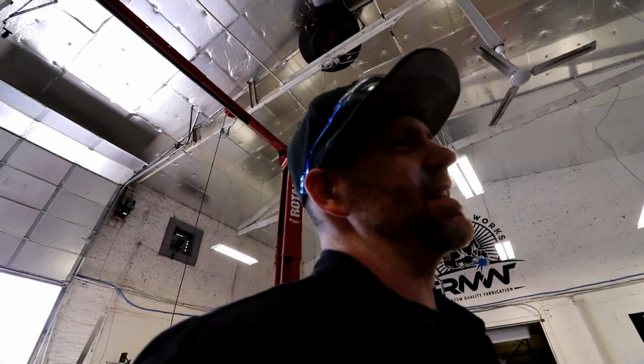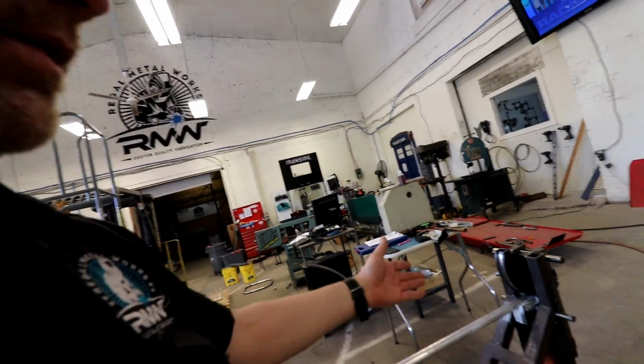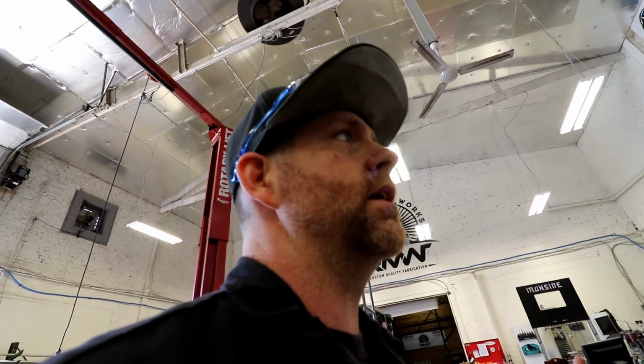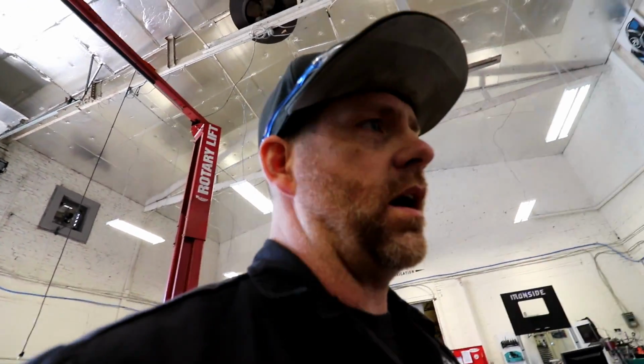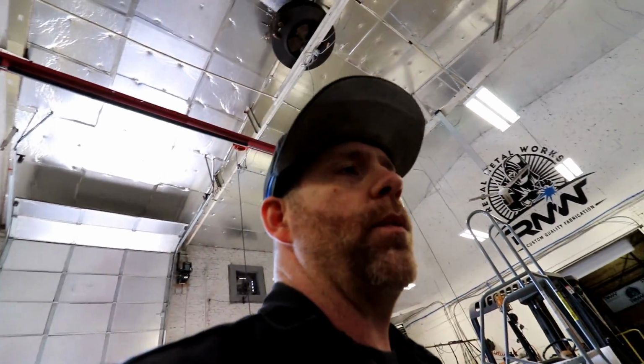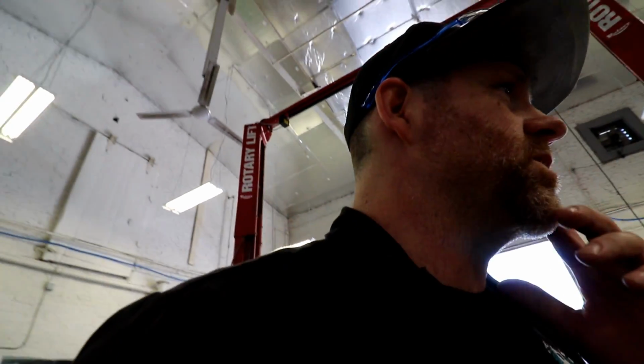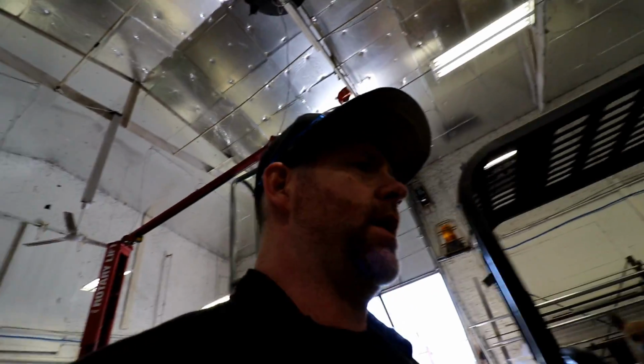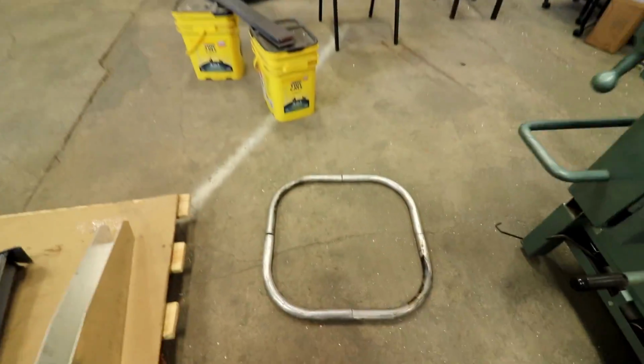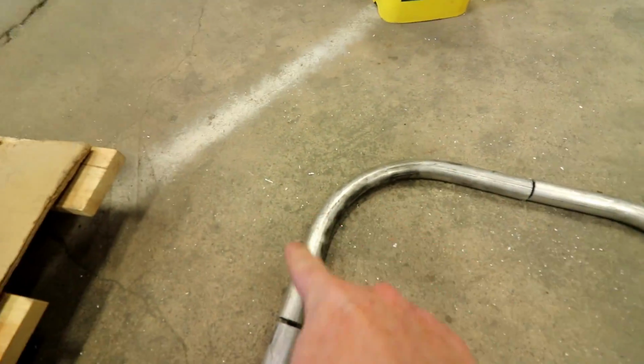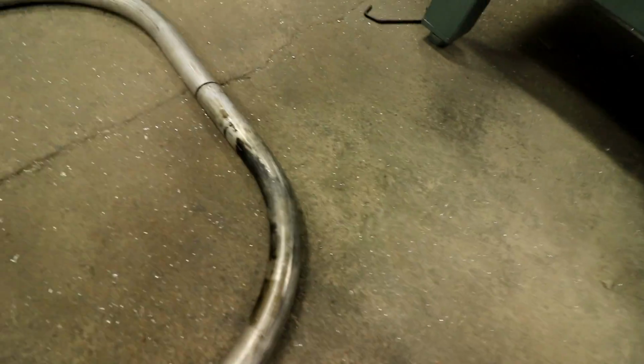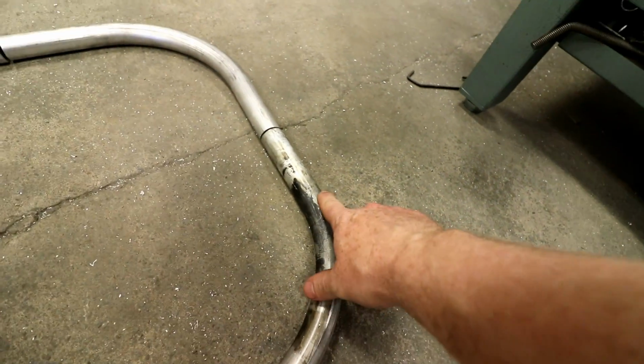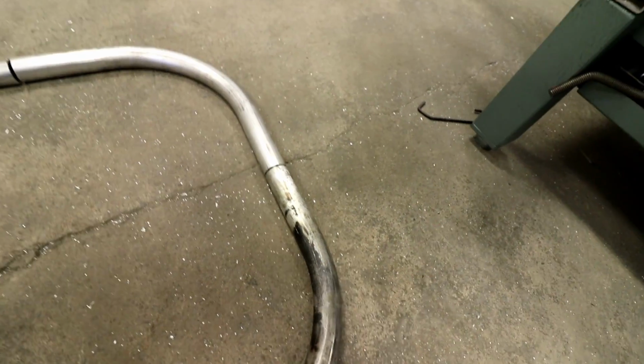Problem with that is it's really hard. You've got a big rod and you're trying to heat it to temper it, or not temper it, you're trying to anneal it. It's hard to get the heat even, so you end up getting it too hot in a spot, not hot enough in another. I did that with a 5-foot piece. I was able to get that bent, and we have some of the results over here, and you can see what I mean. You can still see some of the soot on there, so you can't quite burn it all off. And if you get it too hot, you'll start to deform the aluminum.